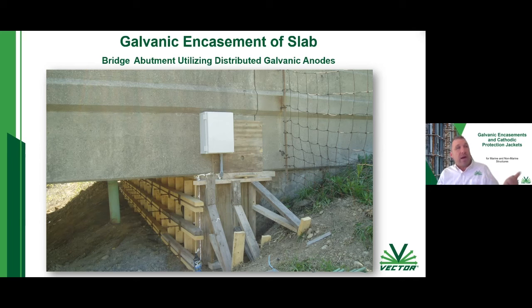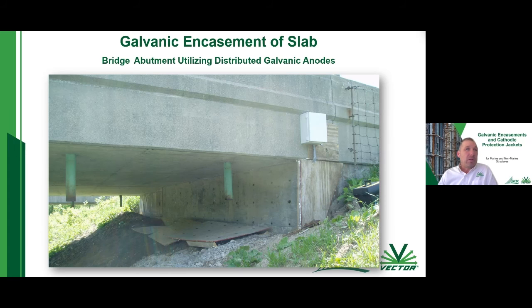So we have all of the anode wires running up to that junction box, and we also have the cathode wires, or the reinforcing steel wires, running up to that box, both from the epoxy coated bar external cage and the original reinforcing steel. We have a data logger in there so that it can monitor the data over time as well. And then this is what it looked like when it was finished, when the forms were being removed.